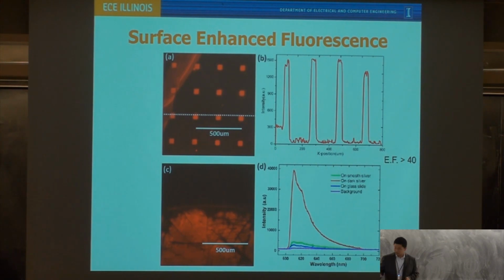The other way we do it is, I probably didn't include the data here, we do surface chemistry conjugation of, for example, fluorescence labeled DNA on the surface, or fluorescent labeled streptavidin or biotin. We can predict the surface density of the molecules, estimate the actual molecule number on the nanostructure or on the smooth film, and then discount that part to get the real enhancement factor readings.